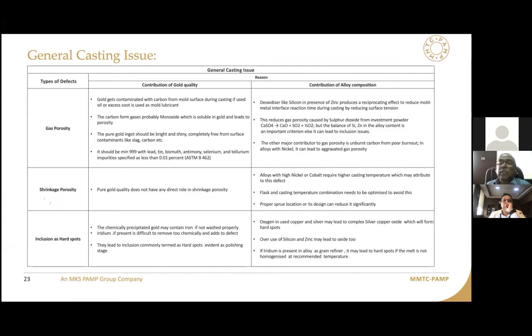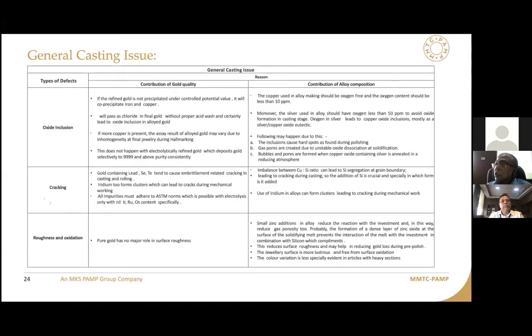If the gold quality is such that, when you pour the liquid gold after your precipitation into a mold where you have applied lots of used oil or soot for lubrication purpose, and then you take out that gold, which is actually laden with carbon, and you don't clean it properly with alcohol or acetone, and you just use it for making alloys and so on, especially if you are doing a direct premixing and casting, then this carbon in the gold, which has got entrapped, will react. It will form carbon monoxide gas, and that will get entrapped into the liquid metal. When that liquid metal gets solidified, it will try to come out of the surface, leaving small micro porosities.